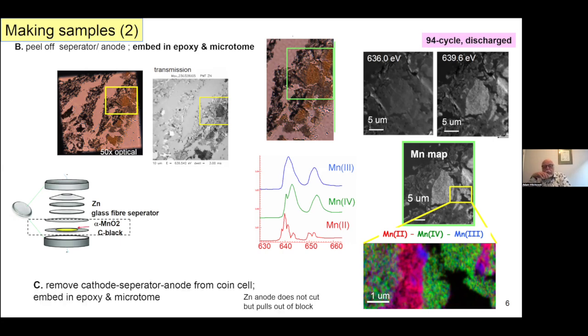We did try a third way, most recent measurements. It was similar to this, but we were ambitious and tried to see also the zinc anode and the glass fiber separator. But these two materials are so hard that when you try to microtome the material, they basically get stuck onto the diamond knife and pull out, so that they warp the structure of the material. So that wasn't very successful.